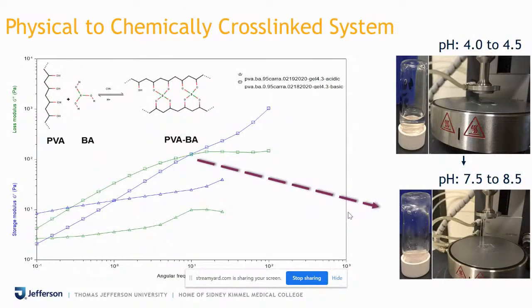Now, I've been giving you an example of the physical system. Now, going to the chemically cross-linked system, where we used the PVA boric acid reaction to form a cross-linking reaction over here, where we mixed it with carrageenan. Now, carrageenan on its own forms a gel which is physical in nature, and so it doesn't cross-link. But we mixed PVA boric acid along with the carrageenan in specific ratios.